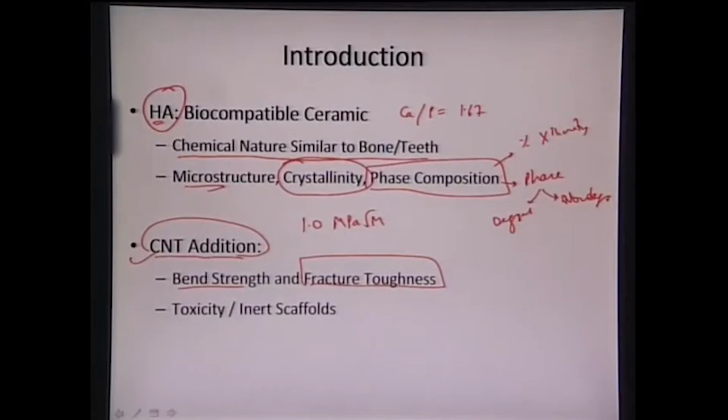But people have seen some effects of irritation or toxicity, whereas another group has also seen apparent precipitation onto the carbon nanotube surface. So we have to carefully weigh these two aspects before we take them for clinical trials. Ideally we are adding carbon nanotube as a reinforcement in the hydroxyapatite to improve its fracture toughness. We also need to confirm whether these scaffolds will be toxic or cytocompatible. So we need to take that into consideration also.